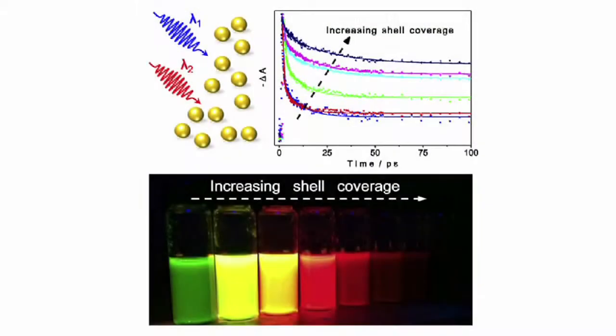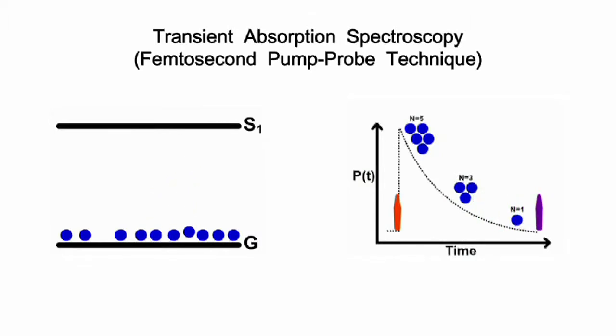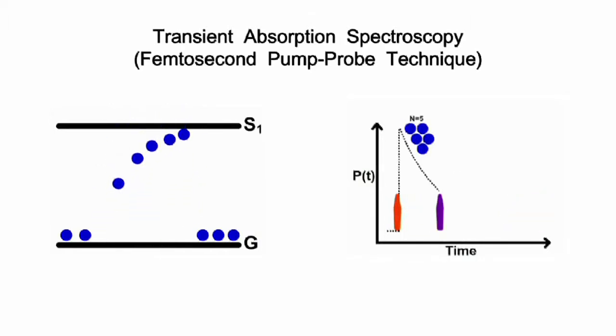Yes, I use femtosecond pump probe spectroscopy to study exciton dynamics in semiconductor nanomaterials. Using a laser pump pulse to excite nanomaterials and a delayed probe pulse to monitor ground state recovery, we are able to understand how fast the charge carriers relax and charge transfer occurs across the nanoparticle interface.